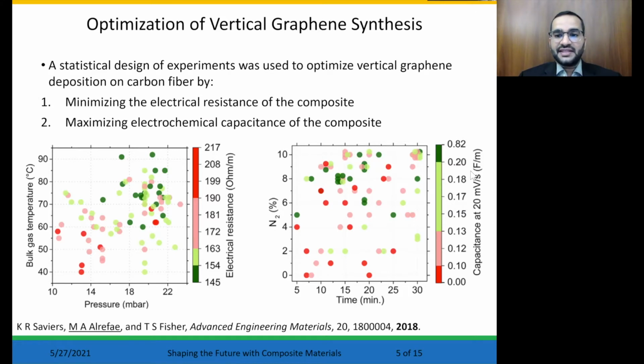The results show that the electrical resistance was minimized at high gas pressure and high gas temperature in the vacuum chamber. The capacitance was found to maximize using a high concentration of nitrogen. The production time, which is an important production factor, has an optimum value of around 15 minutes, after which the capacitance decreases due to possible etching of vertical graphene at longer duration.